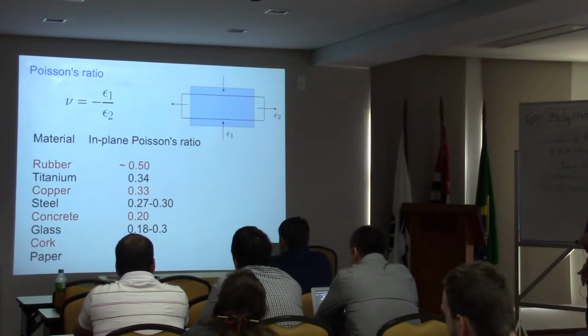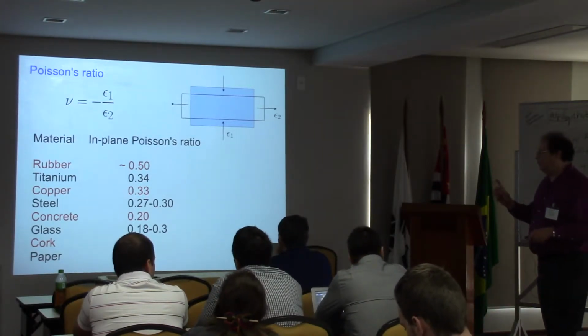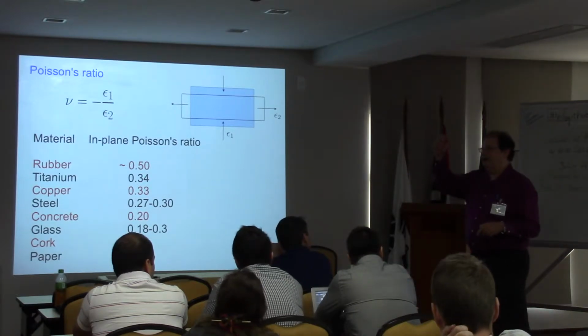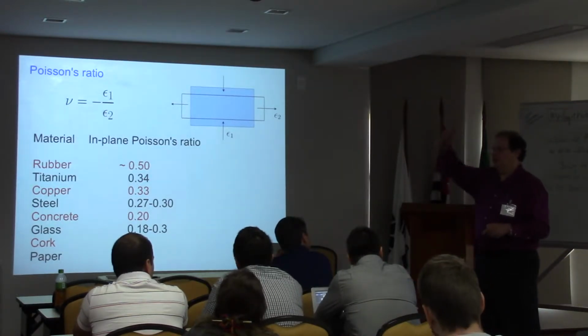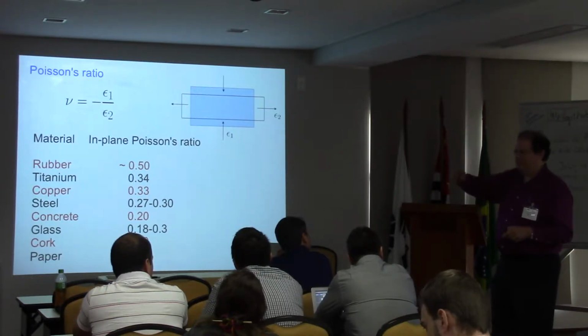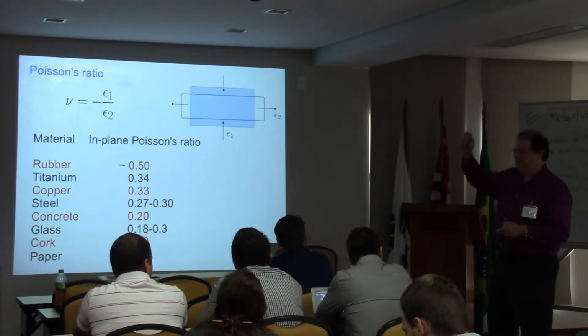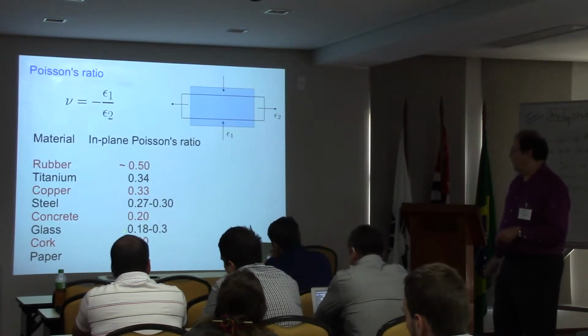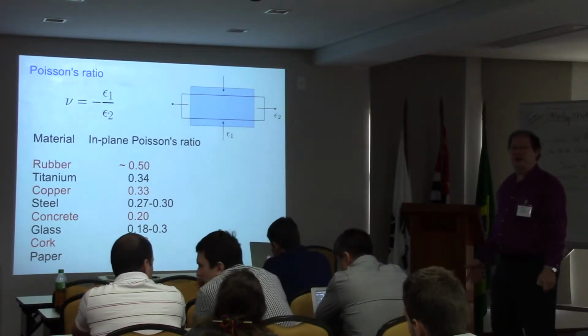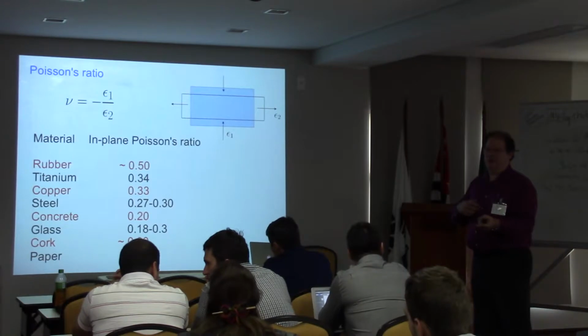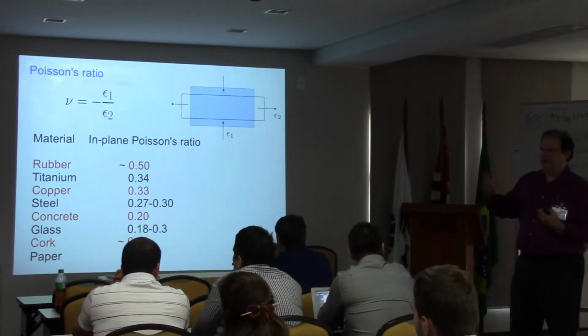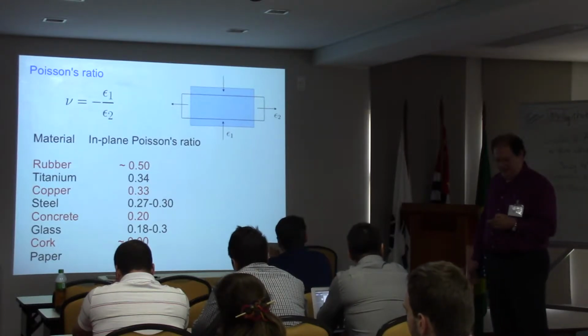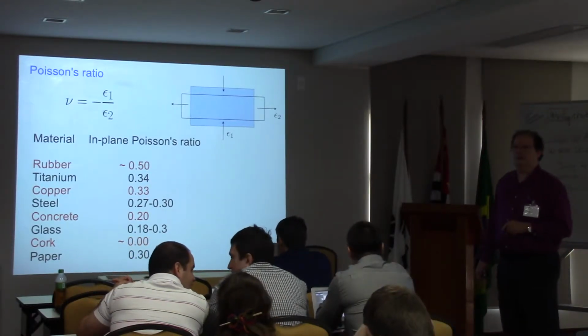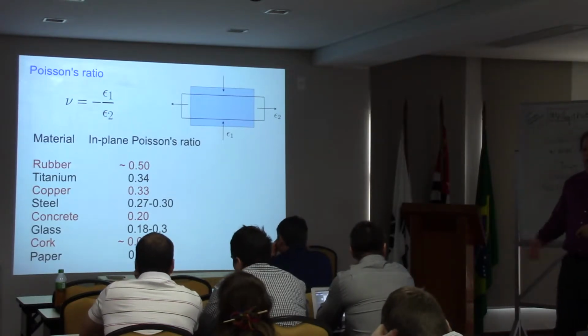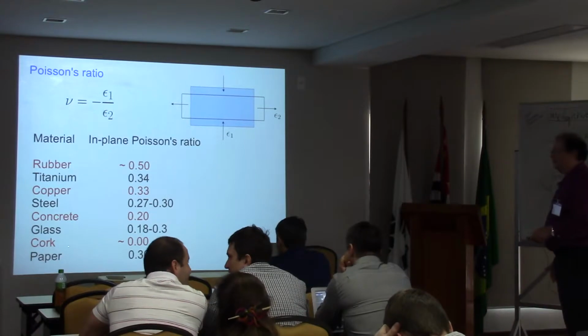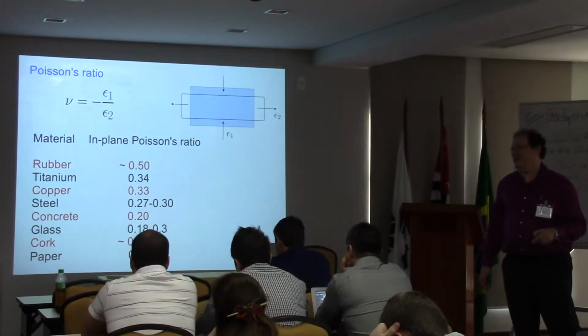One of the most interesting is cork. Cork is probably the only material in nature that has zero. That makes it very ideal for wine bottles, because you do not want it to be very difficult to insert, but you do not want it to be very difficult to remove. So it has to be close to 0. Only cork has this. It has been very difficult in the winery industry to find a substitute for cork. They mix it with polymer, but it's not the same. It changes the porosity, which affects the quality of the wine. So there is no good quality artificial substitute for cork. You do not want to use these artificial corks in high quality, very expensive wines, right?